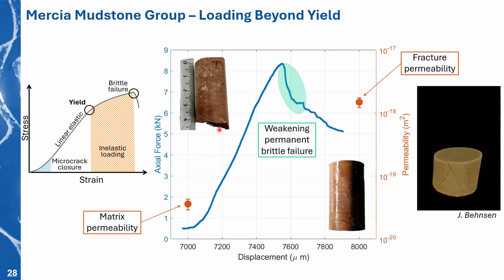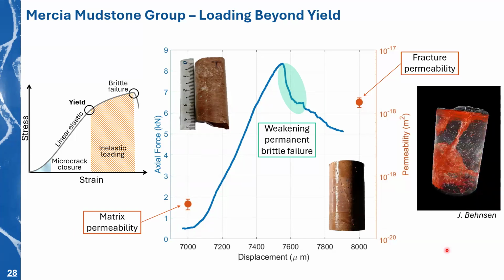Whereas when we have the fracture permeability, so once it's broken and we've got those fluid pathways through it, we've got a permeability that's 2 orders of magnitude higher. So this is perhaps not a good sign for the Mercia mudstone because it's not sealing its fractures and recovering from breaking like we saw in the Ancholme Group sample earlier.